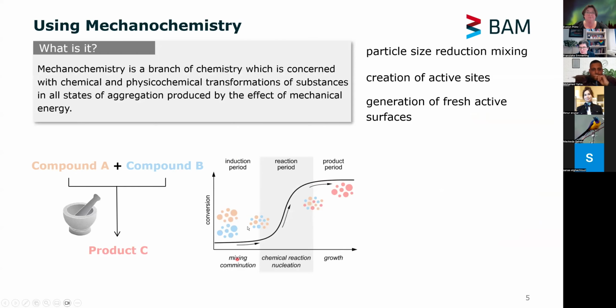Yeah, you have an induction period where you have this mixing, where you form the defects, and then the reaction sets in. If you would stop, for instance, somewhere here, then you have, of course, a mixture of the starting compounds, maybe an intermediate that forms faster and something else. So it is always important to realize how long you should really mill, and that's what we do in the beginning. You know, when you stop after half an hour, and then you see, oh, there's some leftover reactant or whatever, and then you need to work from there.